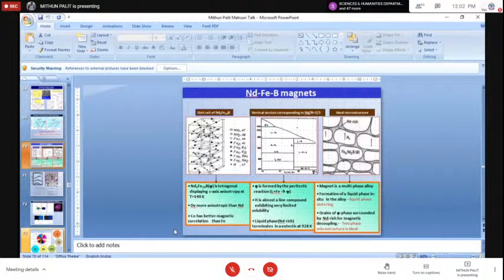Well, all these magnets I talked about so far, that is the Sm2Co17 class of magnet, are all pinning type of magnets by virtue of the precipitates formed. But as I told earlier, there is another class of magnet which has the nucleation type of mechanism, and the neodymium iron boron magnet is one such in this class which has this nucleation kind of demagnetization mechanism.